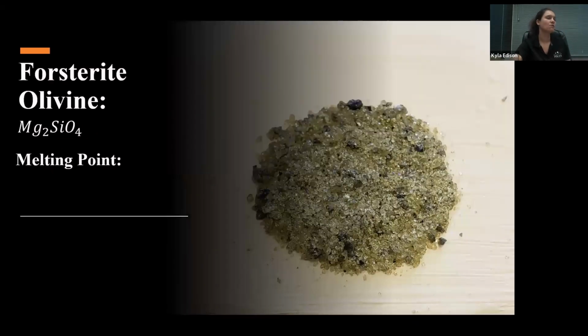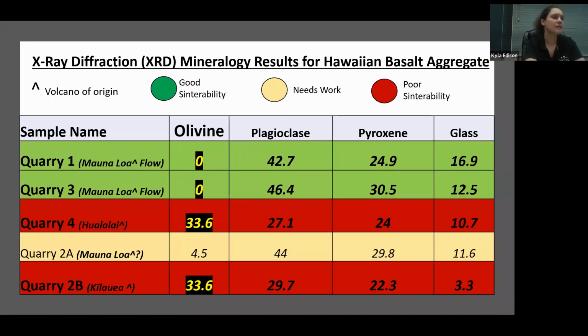And if we look at olivine, specifically forsterite, which is the magnesium end member of the olivine, it's the most common type of olivine you're going to find in these Hawaiian basalts. The melting point for that is 1890 C. That's a really, really high melting point, especially when considering that the highest temperature I'm sintering at is only 1177 C.